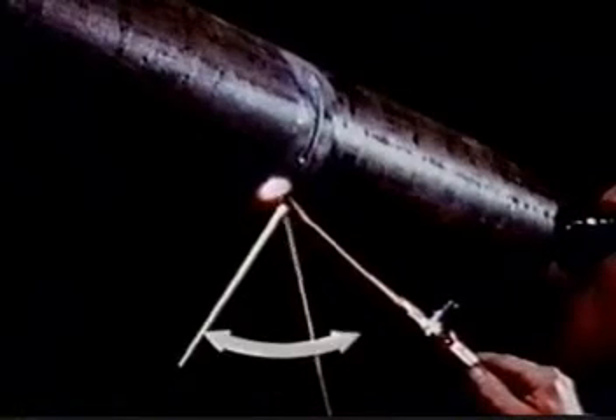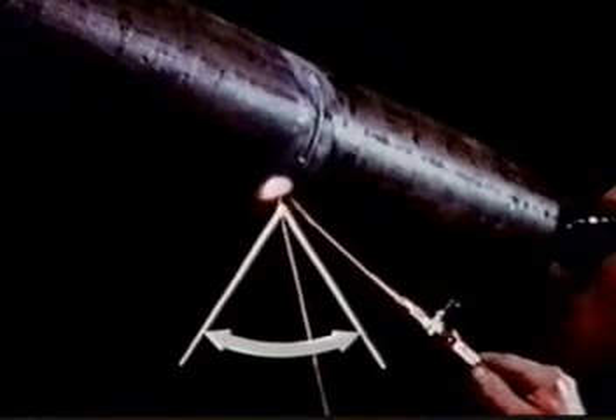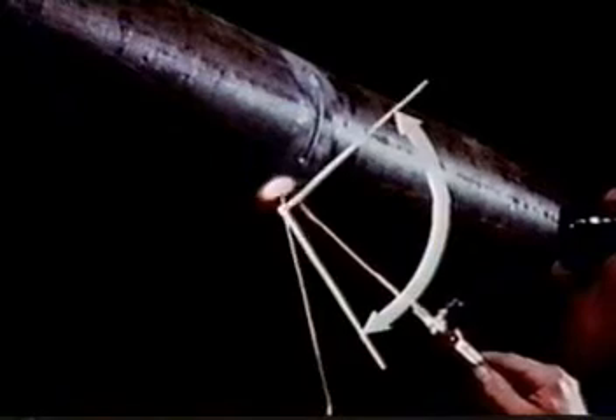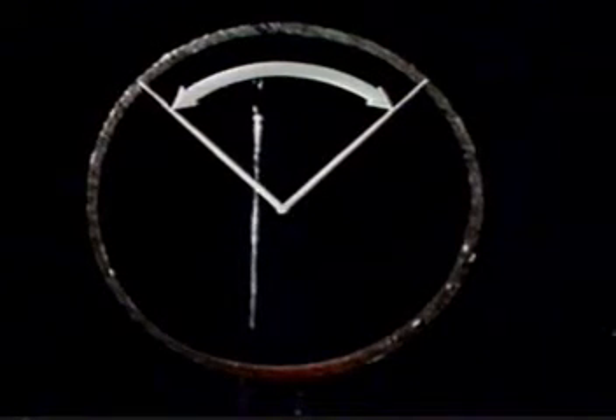A wide field of application of rightward welding is in the site installation of steel pipework, where joints in a fixed position are often met. Simply identified, from 7 o'clock to 5 o'clock, the position is overhead. From 5 to 1:30, vertically upward on a constantly changing plane, and from 1:30 to 10:30, virtually flat. It's important the rod and flame angles are coordinated so that they move progressively, maintaining correct presentation at the point of weld at all times.